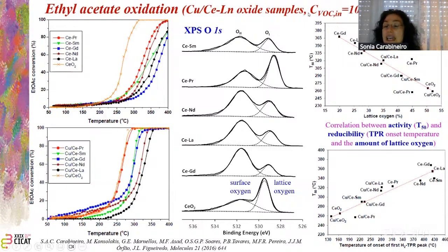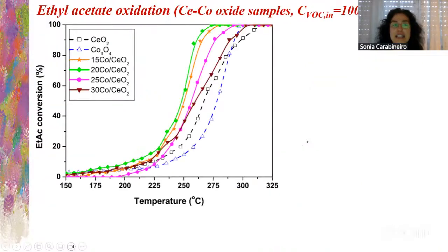The amount of, and also a relationship between reducibility and the amount of lattice oxygen. So the reducibility is seen by the temperature of the H2-TPR, and this one is from the first peak of the TPR. So the lattice oxygen is obtained here from the XPS. So you see, both can have a relationship with the catalytic activity.